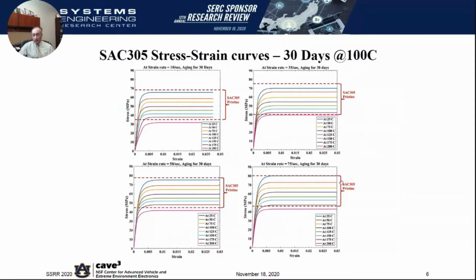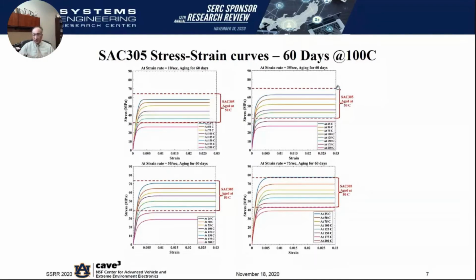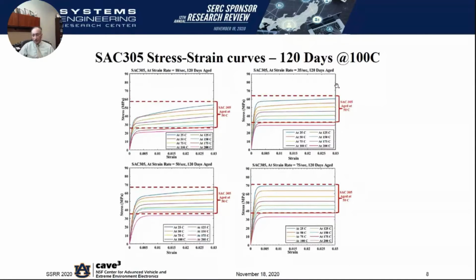And we are comparing this versus a pristine set of curves, and that's what these brackets indicate. So you can actually see that curves start to migrate down with just 30 days of sustained operation at 100 degrees centigrade. So the next 3 slides are somewhat of a pseudo movie. I'll flip through them so you can see what's happening with the curves, and they're at 60 and 120 days successively. So you can see how the curves behave. This is 60 days, and that's 120 days, excuse me, not 90 days.